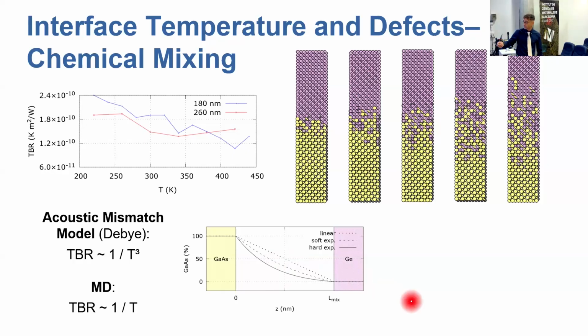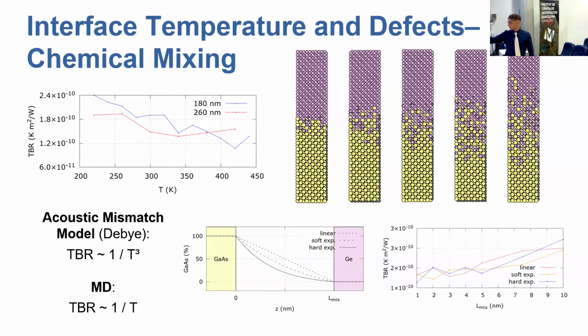In particular, the linear decay of the concentration, the soft exponential decay of the concentration, and the hard exponential decay of the concentration. Still, in the 3 cases, we repeated the simulations for something like 20 more simulations, for the 3 decay kinds. And you can observe that there is a rather linear increase in the thermal boundary resistance with respect to the mixing length, regardless of the specific concentration decay, which was rather interesting because we would have expected that somehow the difference in the concentration decay would have affected the dependency, but no way. The mixing length is the only parameter affecting the TBR at this level.